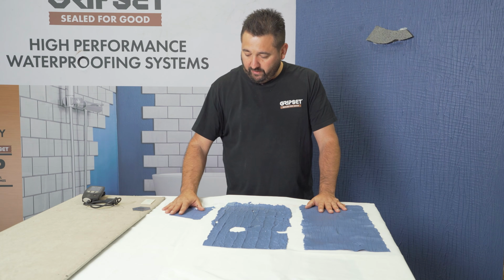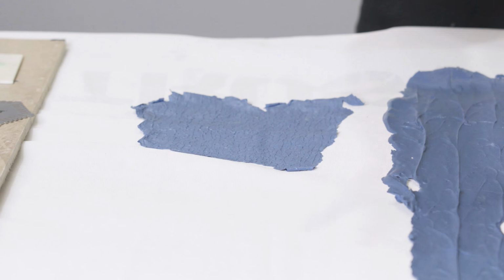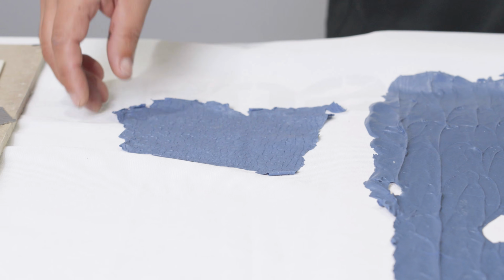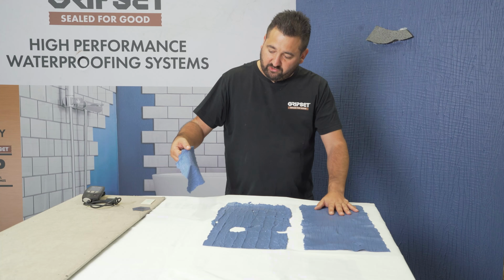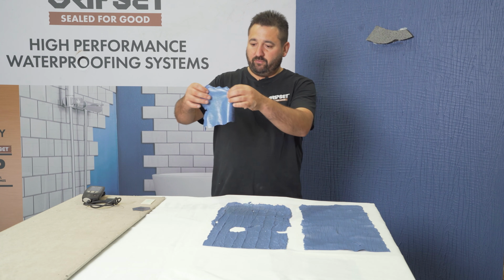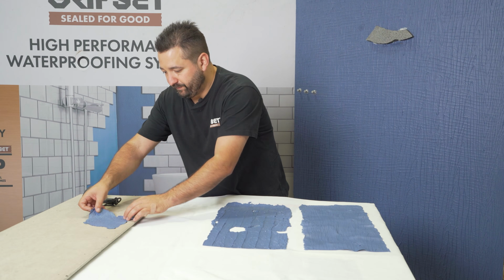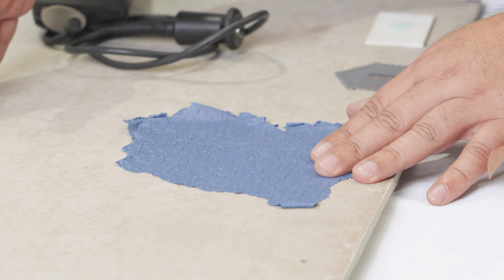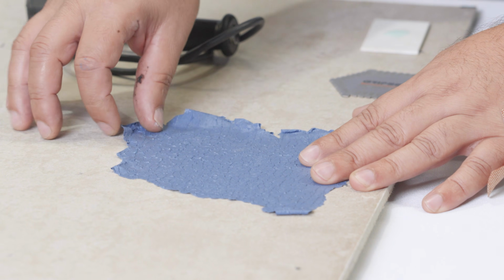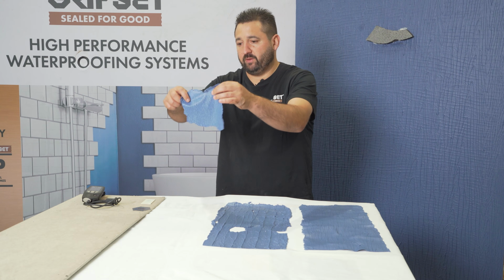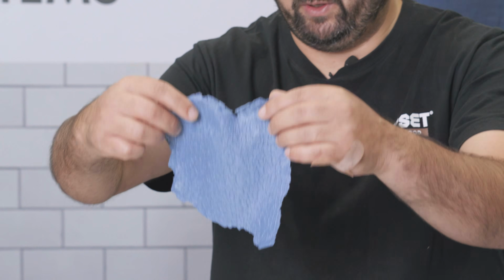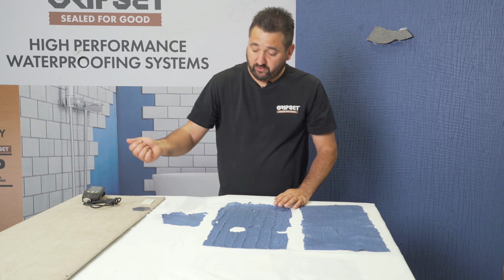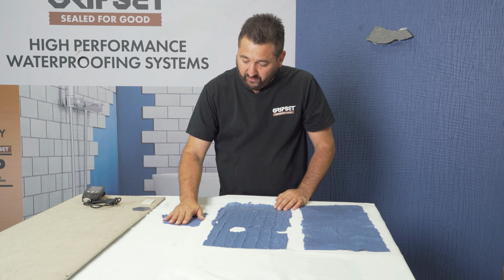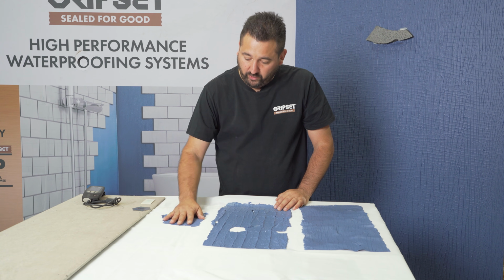So over here, I've peeled it off the sheet. All of them, all the specimens were the same size, but because this one's been applied at such a thin coat, it's almost translucent. But if you put it up against a substrate, it does look like a coated, fully coated system. But when you actually take it off, you can see it's very, very thin, paper thin. So when I was pulling it off the sheet, because it's thin, it's weak. And because it's weak, it tears.